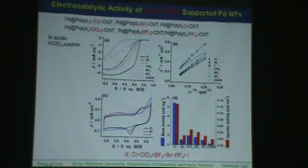Other studies also indicate chloride anions show the highest electrocatalytic activity. The second is perchlorate, and then BF4, bromide and PF6 are more or less the same, but iodide has quite low catalytic activity. This means the electrocatalytic activities are largely influenced by the counter anion of the imidazolium moieties.